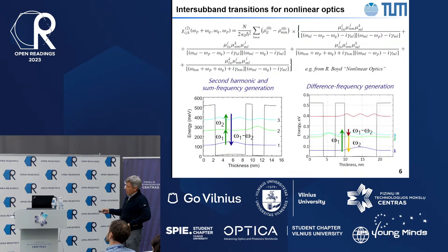We can play with the thicknesses of these wells and barriers, and we have simulation tools that can simulate the wave functions. We can play with these simulations to maximize the product of three transition dipole moments between the three states, let's say 1, 2, 3, so as to maximize the nonlinear response for a particular process. We further can tune the resonances to match the desired nonlinear process and further maximize it by the resonant enhancement. And then we could use the existing technology to implement everything that we are designing, and we could really see how it functions.